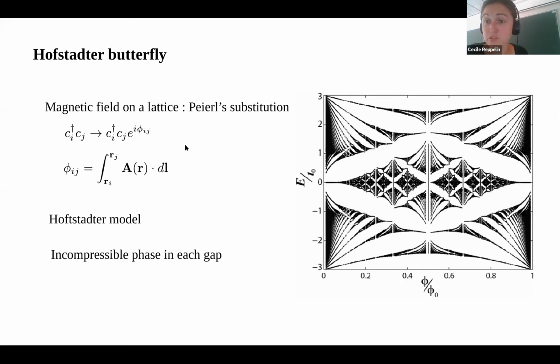And if you solve the Hamiltonian in that case, or Harper's equation, this will give you a spectrum which has a self-similar structure. It is fractal. The way to look at this is to fix phi, the flux quantum, and the y-axis corresponds to the energy. Each gap within the spectrum corresponds to an incompressible phase. If you are at small flux, you'll recover your typical Landau levels, but as you go more towards phi equals phi naught, the unit of flux quantum, then you have a very different physics.